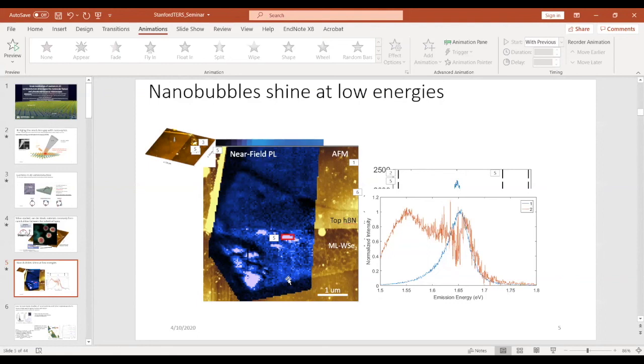How about the reproducibility of nanobubbles and size of nanobubbles? They vary a lot in sizes. They're reproducible in that you tend to get most of them in the one nanometer to 10 nanometer height. Bigger ones are comparably rare. Smaller ones are hard to see. They tend to be in that range. The strain distribution when they're in this limited size, at least if you assume a uniform plate, is actually about the same. They tend to have a uniform aspect ratio when they're of this size. So you have about 1% strain in nanobubbles of all sizes. The pressures inside are very different. Maybe a half nanometer size nanobubble has gigapascal pressure versus maybe 200 megapascals for a hundred nanometer radius bubble.